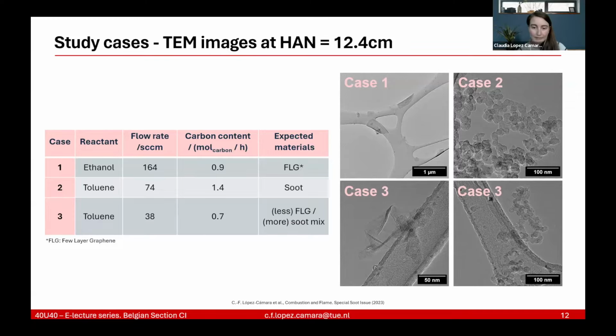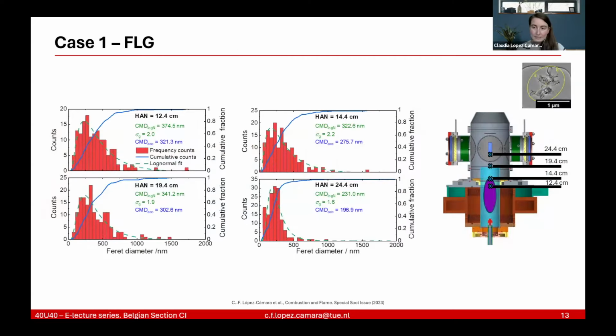So we wanted to understand a bit more about the evolution, how the graphene and the soot look from the beginning to the end where we collect it in the filter. So looking into the graphene, which is case 1, we made some histograms accounting for the size of the graphene, and the way that we described the size was by the Feret diameter, which we identified when we had a very crumpled graphene. Usually we draw an ovalene, as you see in the picture on the top right. We draw an ovalene surrounding the full flake, and we take the largest diameter of the ovalene as our Feret diameter. And that's what we took as a reference dimension and as a reference measurement.